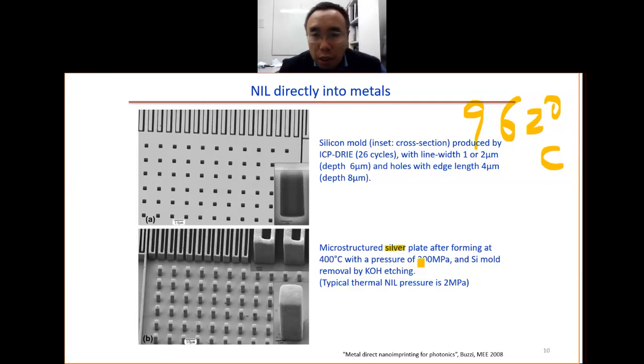They use 300 megapascal pressure. Normally when we do thermal imprint, we only need 2 megapascal. But here it is a moderate temperature and very high pressure. So this is the mold. This is the silicon mold made of silicon using deep RIE. With this deep RIE, again, you see the wavy structures. So this uses the Bosch process.